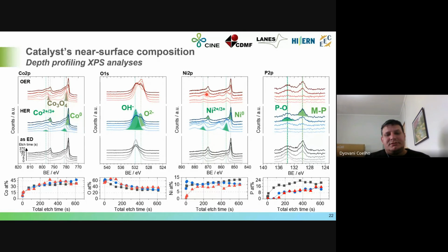And for phosphorus, the results show that phosphorus is not stable at all. Just by putting the catalyst in the electrolyte, the phosphorus on the surface is completely dissolved. Even under the surface, the phosphorus is completely dissolved. We don't have any phosphorus on the surface and even close to the surface.